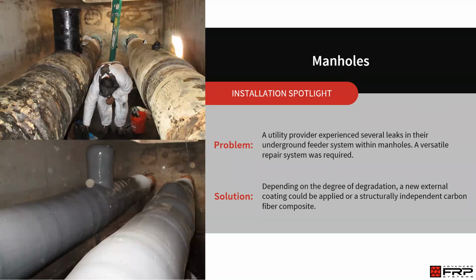So we see varying degrees of degradation in manholes, and you often can't tell how bad your manhole is until you completely remove the existing coating and do an assessment. So what we did was we developed a versatile repair option. If you remove all the coating and there's significant corrosion, we can fully structurally reinforce the manhole feeder with carbon fiber. If there's less significant corrosion, spot structural reinforcement can be installed, or you can do a partial structural reinforcement where you're just enhancing the strength of that steel pipe. Finally, you could just do a better protective coating system, a newer coating system, to allow you to get a long-term life extension.